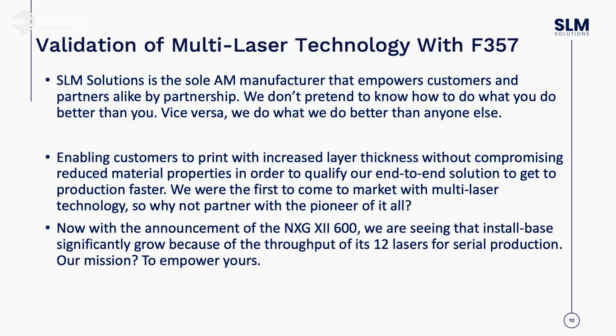So when companies begin to move from laboratory additive manufacturing to production additive manufacturing, like anything, time is of essence. And the industry has moved from 20 and 30 micron layer thicknesses to now we're printing with customers at 60 micron, and we're in development with 2 customers to print aluminum at 90 micron. Now you can go to thicker layers, but you still have the requirement of meeting design intent.